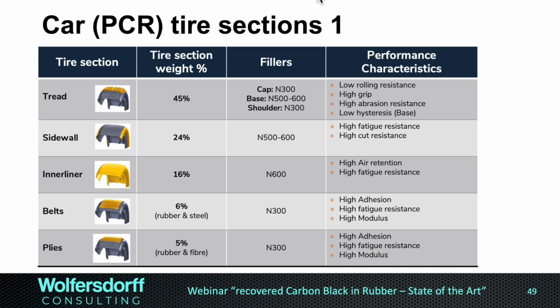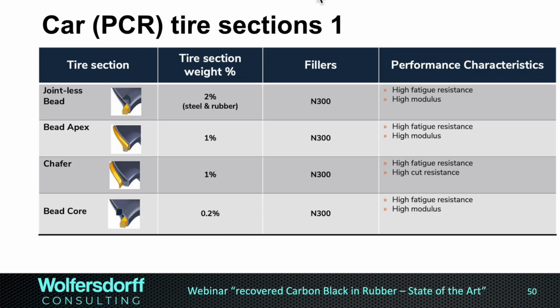And then it gets really small, and tire makers are reluctant to change much in the smaller compounds because the risk with the smaller compounds that the compound is not working for a very small amount of change in sustainable material is getting much too high. So we have the jointless bead, we have the bead apex, the chafer, bead core. Tire makers are very reluctant to change anything in those compounds because they make such a small section of the tire, and the sustainability gain they can get by putting recovered carbon black there is very small, and the risk of actually risking any mechanical issues, delamination, is much too high.